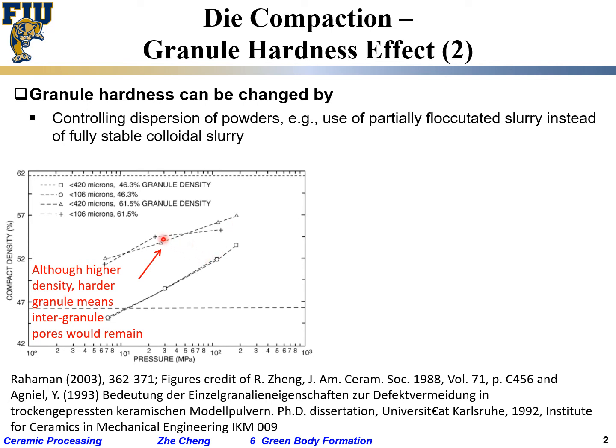So in reality, this one may not be ideal because within your granule, your packing density is a little bit too high, which means your granule does not want to crack, deform, and fill in to the higher density, even though initially it has higher density.